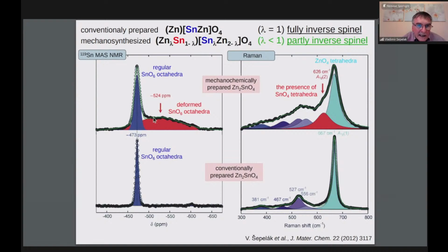conventionally prepared zinc stannate. You see this additional red subspectrum corresponds to deformed SnO6 octahedra, and this blue subspectrum is associated with regular SnO6 octahedra. That means we have additional deformation of the structural units in the structure of this mechanosynthesized material. And here is the same comparison for the Raman spectra. We see also here in the case of mechanosynthesized material additional spectral components which indicate the presence of SnO4 tetrahedra. As we know, tin in the conventionally prepared material occupies only octahedral sites. That means this is an indication that we have a partly inverse spinel.